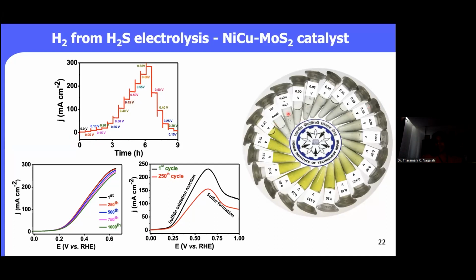And at the same time, you can see the color going from colorless to pale yellow, and the color is increasing. So this is due to the production of polysulfide in the solution, and with increase in time, the turbidity of the solution increases, because we still have a lot of polysulfide in the solution. However, when you switch back this one, this is the beauty of the experiment.